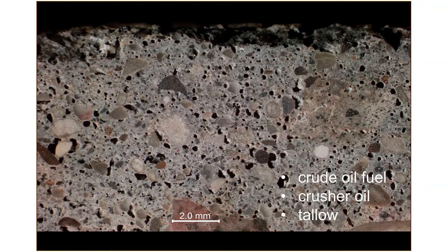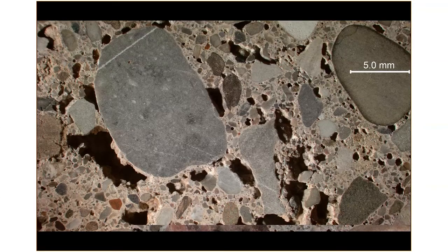So we look at the lower lift of this concrete pavement, and we see lots of large voids, under consolidation, and again the gap graded nature of the coarse aggregate, having some 1.5 inch aggregate in there, so 3/4 inch aggregate, and again the torpedo sand and all that, mixing this in a very chunky nature, and then tamping it into place.